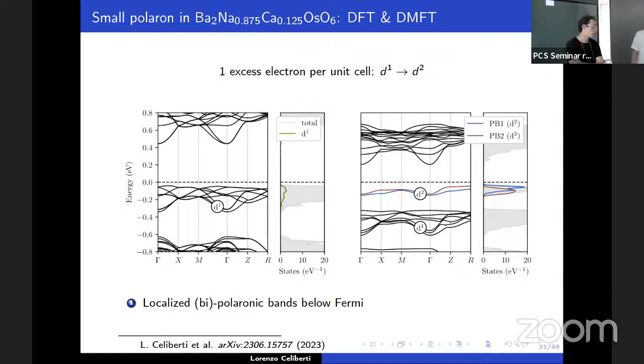For this d2 polaron in your calculations, you said you kept the magnetization of the site zero? No, it's not zero magnetization. Actually, it's larger for this polaron because you have one electron more, so they tend to align. But this, in no way, we don't know.